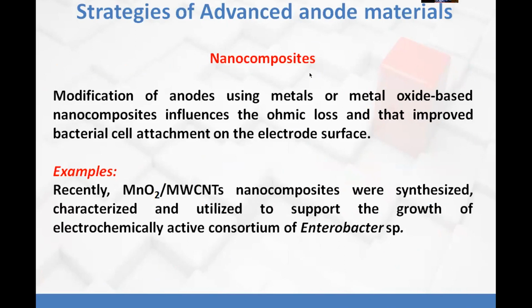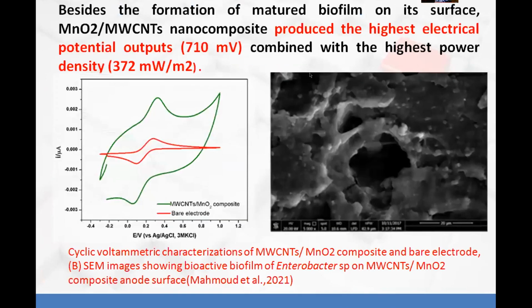This nanocomposite may be a metal or oxide-based nanocomposite that affects the ohmic loss and improves bacterial cell attachment on the electrode surface. For example, manganese oxide and multi-wall carbon nanotube nanocomposite is used for supporting the growth of the electrochemically active consortium of Enterobacter. Besides the formation of matured biofilm, this composite produces a high power density of 370 and potential output reached 710. And as you see, this is the electrochemical characterization of this nanocomposite compared with pure graphite, and this is the same characterization of the biofilm produced on the surface of the anode.